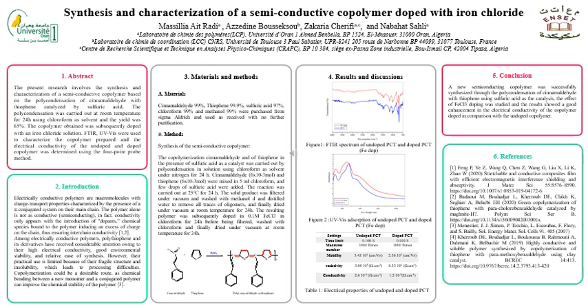We have therefore suggested to copolymerize thiophene with cinnamaldehyde using sulfuric acid as the catalyst in the presence of chloroform as the solvent. The copolymer obtained was subsequently subjected to doping using an iron chloride solution.